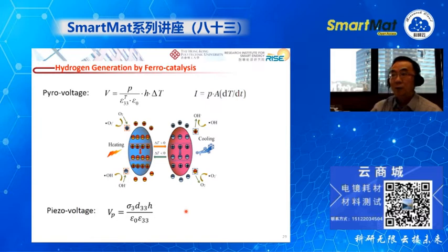And if you cycle the temperature change or cycle the applied stress or strain, then the surface of the pyroelectric material will have surplus charge being released under the external cycling of the temperature or the applied stress. And this released charge will participate in the oxygen evolution or the hydrogen evolution if the conduction band edge or the valence band edge are suitable for the water splitting.